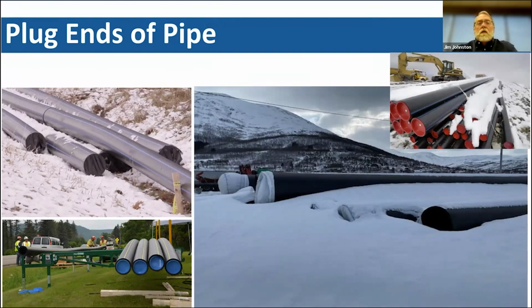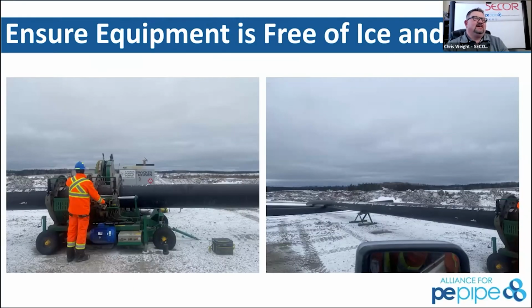Well, keep in mind on that, Jim, when they're capping the end of the pipe, you want to cap that pipe when it gets to the job site. Yes. Don't wait until the day you're going to fuse it, because at that point you're already full of ice and snow and critters that are hiding from the cold elements. Yep. So as that pipe's showing up, stick your bag over the end or whatever you're going to use. Do that when the pipe shows up on location, because when it comes from the factory, it's as clean as it's going to get inside. Yep. And the last thing you want to happen is have a skunk squirt in the middle of your pipe during the middle of a fusion. That'll ruin your day.